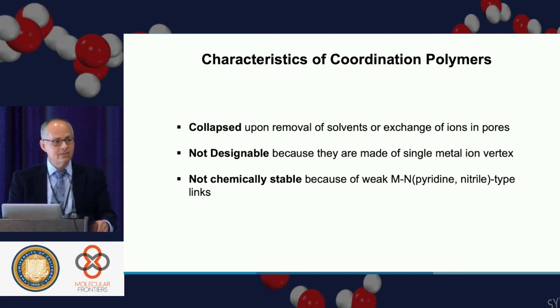Whenever you try to exchange the ions or exploit the porosity, they collapsed. They were not designable because, as you know, copper-1 could be tetrahedral or it could be trigonal. So you couldn't quite predict. And definitely they were not chemically stable. They were made from weak bonds. And in fact, some of those dissolve when you put them in organic solvents. So that was the problem that we faced when I was assistant professor.